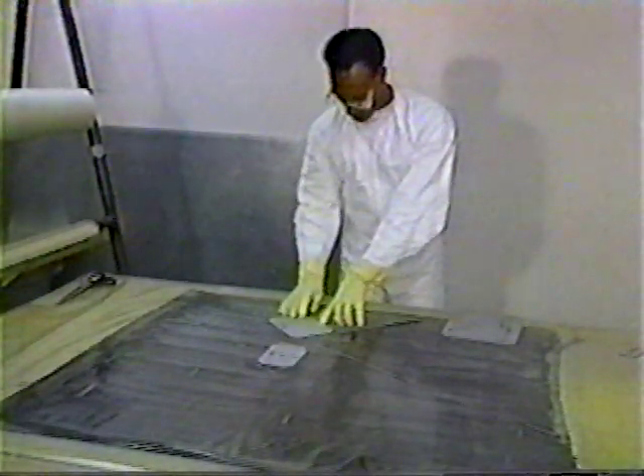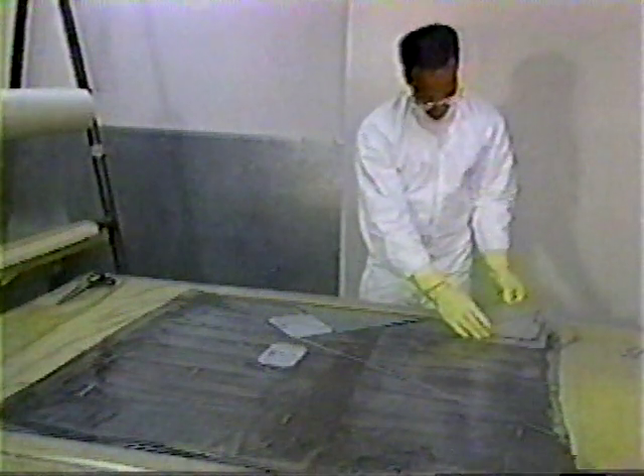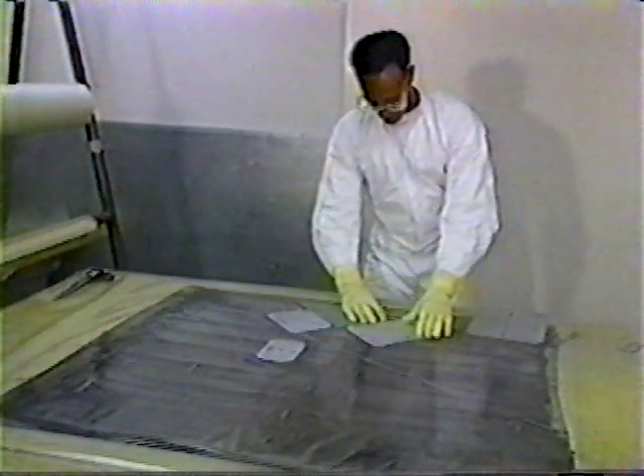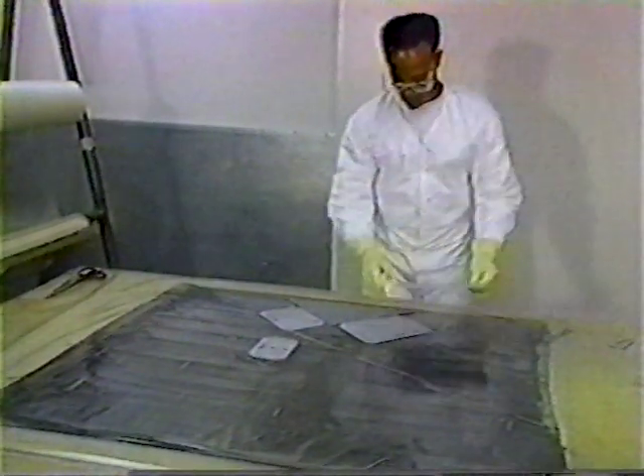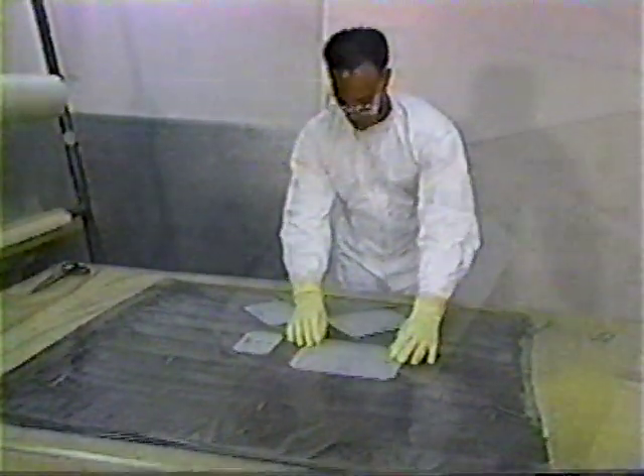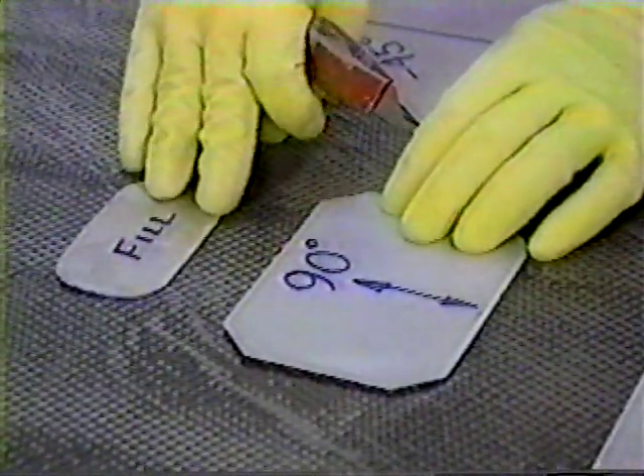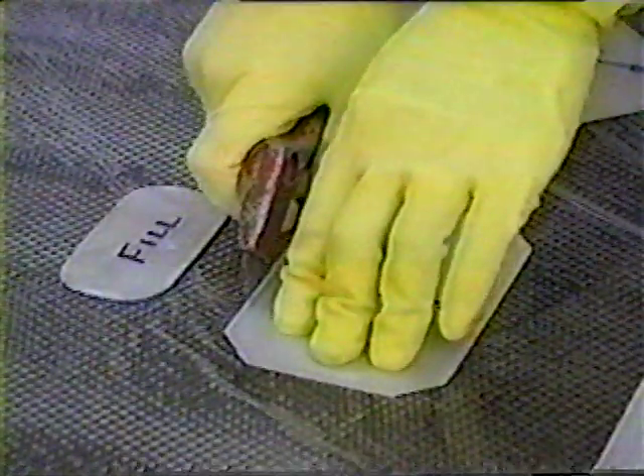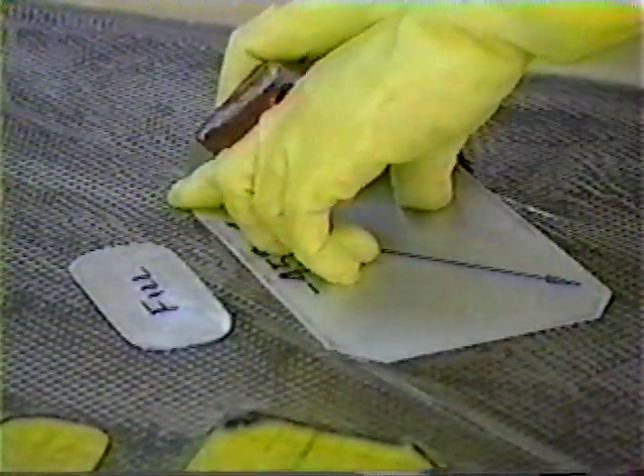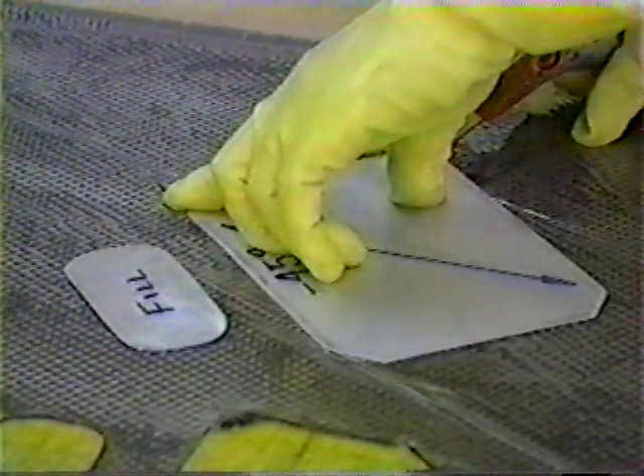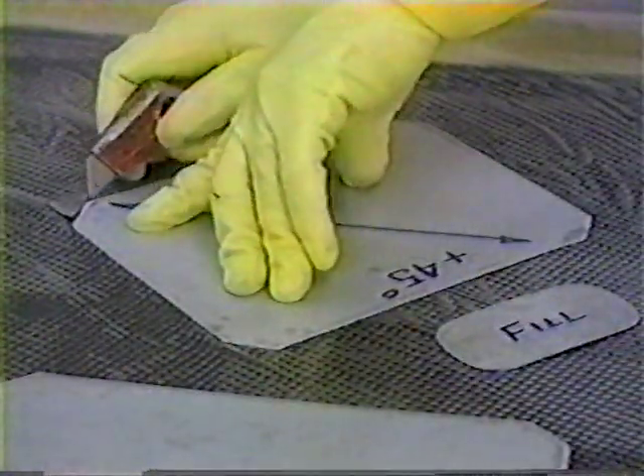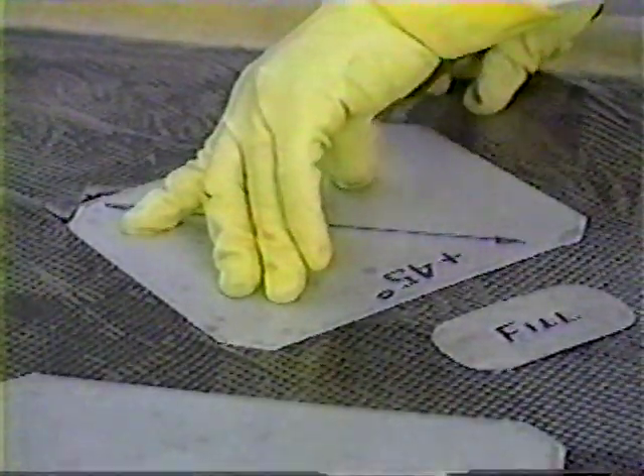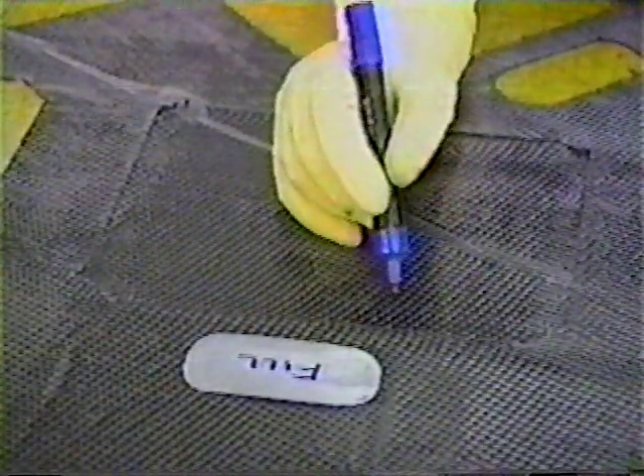Lay out the sheet metal templates on the material so that the warp orientation for each repair and fill ply matches the orientation called out in the SRM or the engineering drawings. The SRM for this particular panel requires the first ply for both the fill and repair ply be cut with the warp toes running in a 90-degree direction. The second set of fill and repair plies are cut with the warp toes running at -45 degrees. The third set of plies are cut at +45 degrees. And finally, the fourth set of plies are cut with the warp toes running in a 0-degree direction.